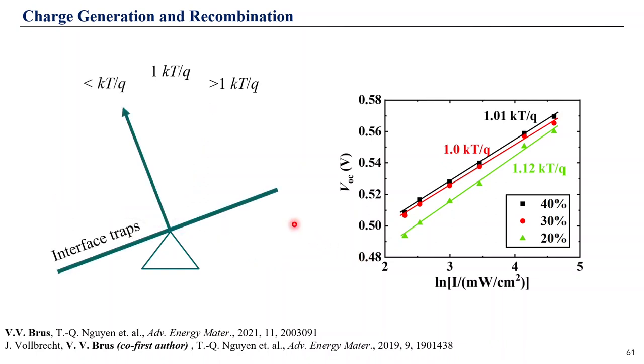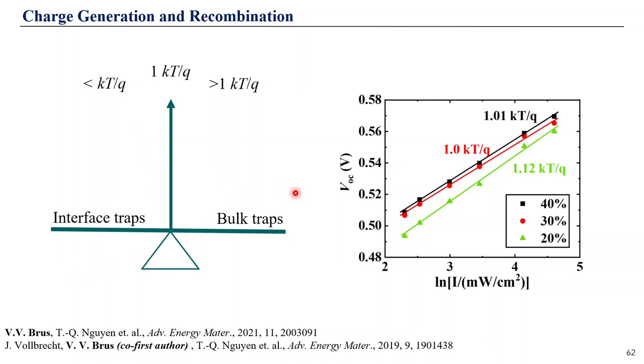At the same time, there is another possibility: surface recombination between the active layer and the electrode, which results in a slope smaller than 1 kT over q. That's why we need to consider the possibility of multi-mechanism recombination dynamics, with bimolecular and trap-assisted recombination in the bulk and at the interface. In that case, the bulk traps may counterbalance the interface traps in terms of their effect on the slope. And we end up with a VOC versus light intensity slope close to 1 kT over q. However, it's not evidence of pure bimolecular recombination, but just complex recombination dynamics. And that, unfortunately, is quite often misinterpreted in the organic photovoltaic community.